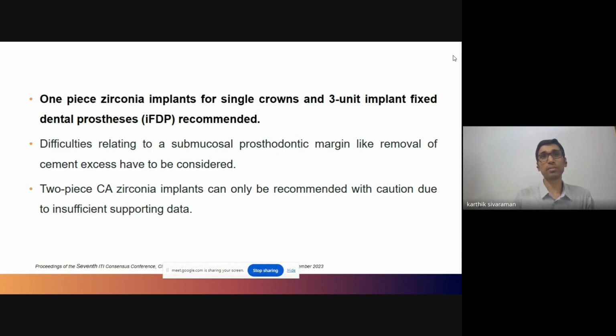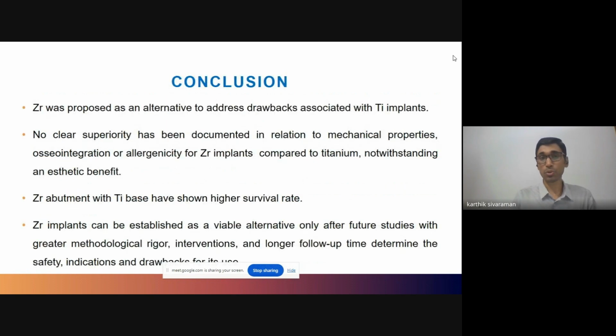So this shows that the body is quite cautious when it examines the existing evidence, and we still cannot say that zirconia is as versatile or dependable as titanium, which is the existing gold standard for any implant material in the market currently. When we speak about a single-piece implant, they also recommended that the difficulties relating to submucosal prosthodontic margins, like removal of cement excess, be considered, so that the health of the peri-implant tissues is not compromised and can be maintained. So to conclude, zirconia was proposed as an alternative to address the perceived drawbacks with titanium implants.